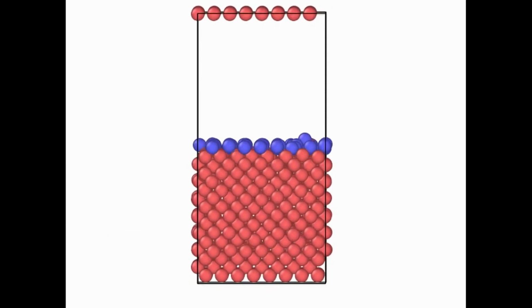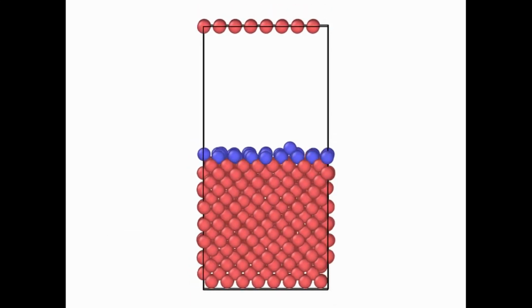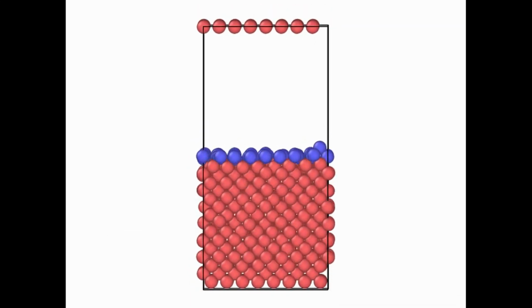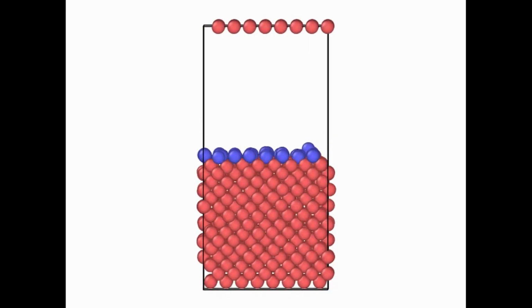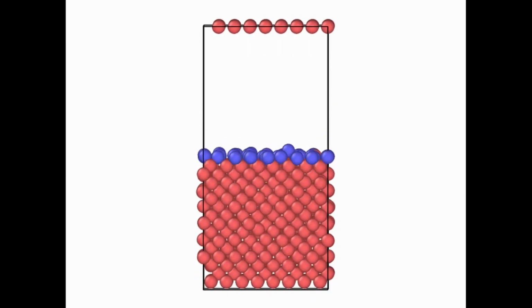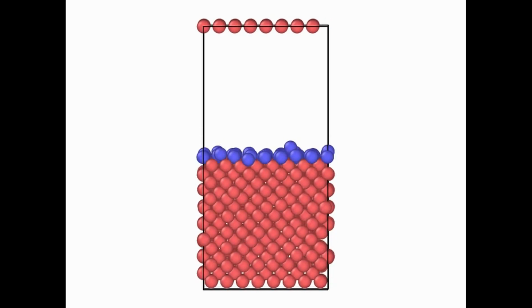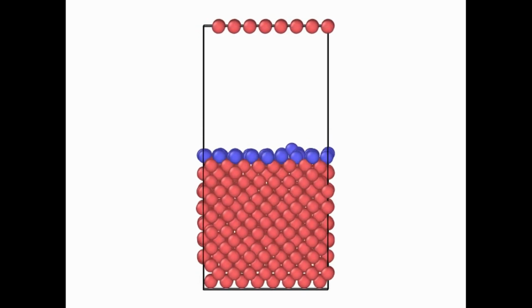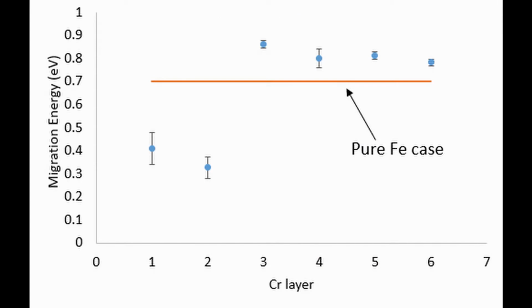We noticed in the layer tests that when we had the surface be completely chromium, the surface would, at the beginning of the simulation, immediately absorb the iron atom and kick out a chromium atom. So throughout the simulation, the adatom was simply chromium. We noticed that the first two layers of chromium had significantly lower energy and therefore higher mobility. They also had a lot more error because, especially as temperatures increased, there were some effects like mixing of chromium atoms into the bulk. Sometimes there would be two adatoms, and those would create inconsistencies in the diffusivity.